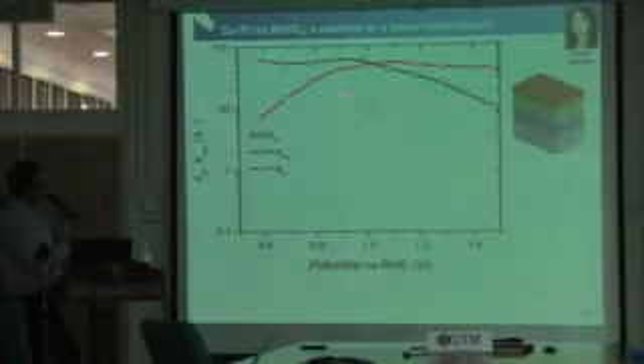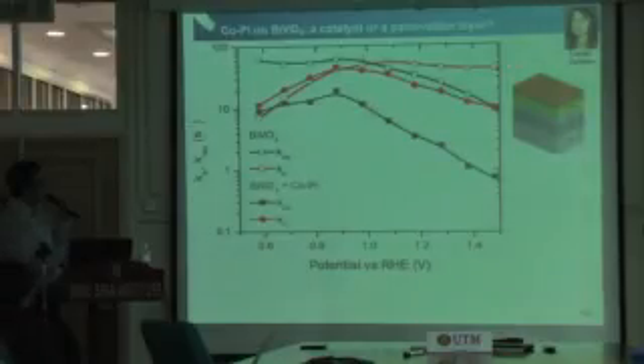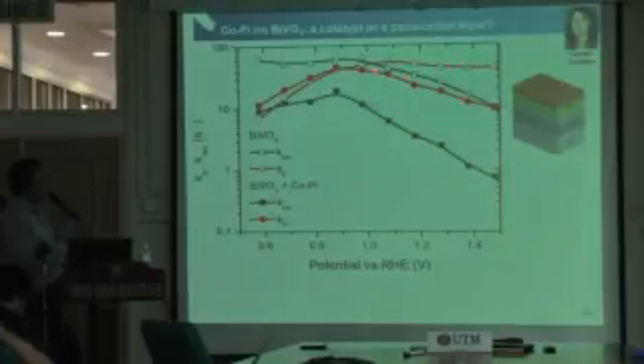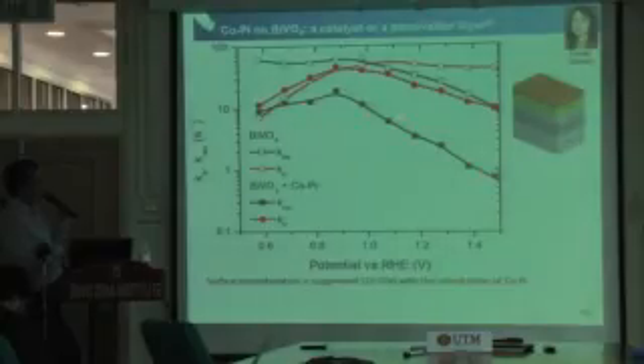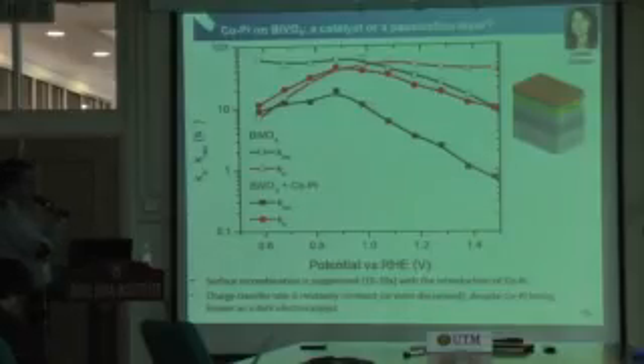Recombination rate is black, and the charge transfer rate is red here. As soon as we put the cobalt phosphate, if it's an electrocatalyst, you would expect the charge transfer to go up. But instead, we see that the charge transfer goes down, and the main effect is actually in the charge recombination. So we see that the surface recombination is suppressed by a factor of 10 to 20, and the charge transfer is relatively constant or even decreased, despite cobalt phosphate being known as a dark electrocatalyst.